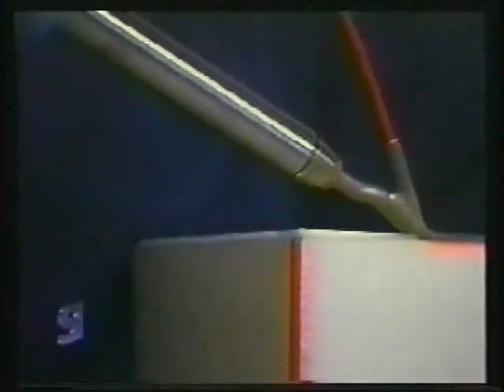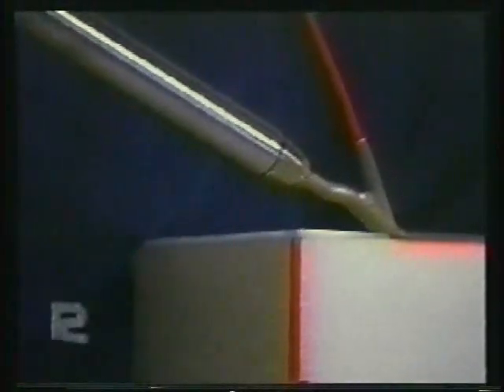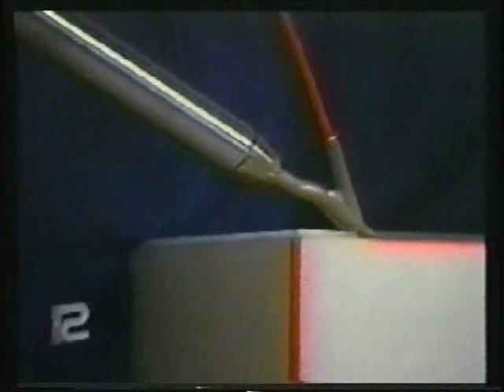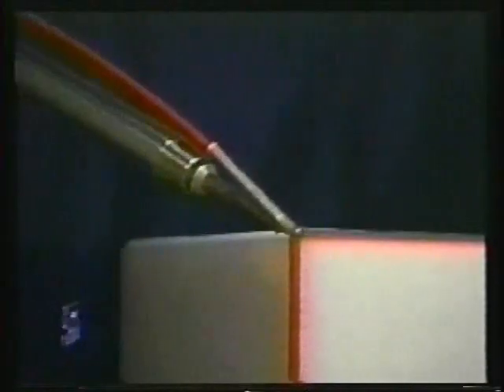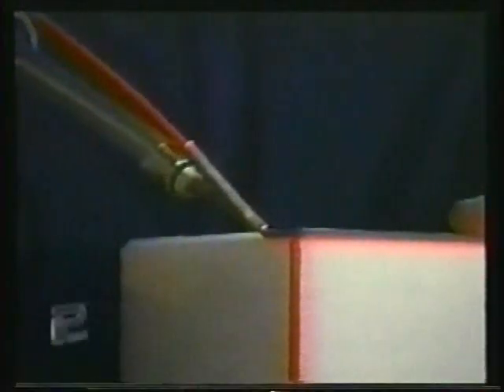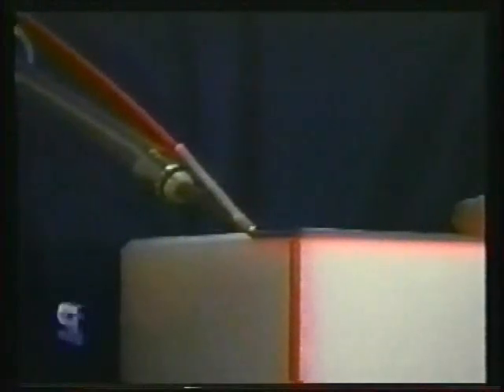Continue a steady, smooth motion along the seam without stretching the welding rod. Keep a consistent downward pressure on the welder and watch for the slight juicing on each side of the weld bead, indicating your temperature, speed, and pressure are correctly being applied. The speed tip will increase production 5 to 6 times faster than hand welding and helps eliminate long-run hand fatigue. It will also produce a long uniform weld.